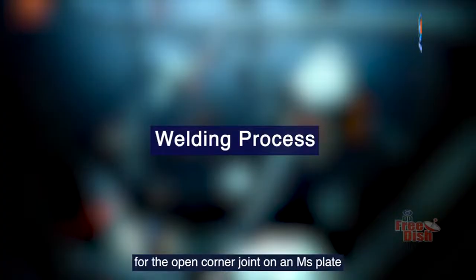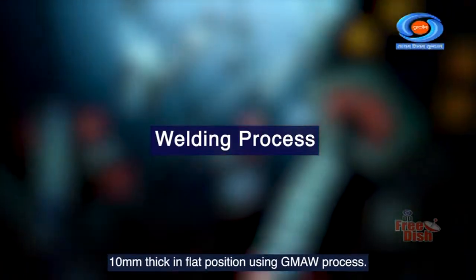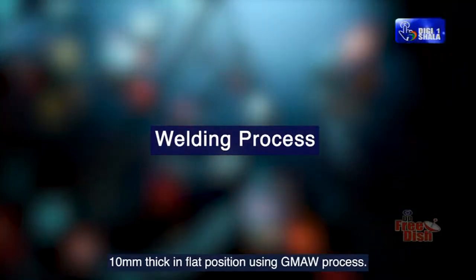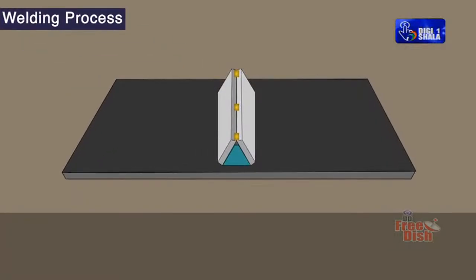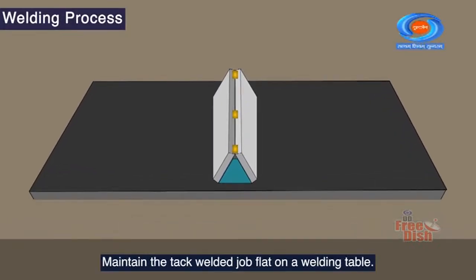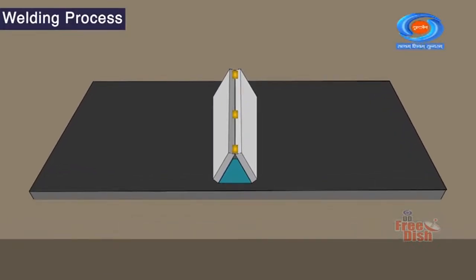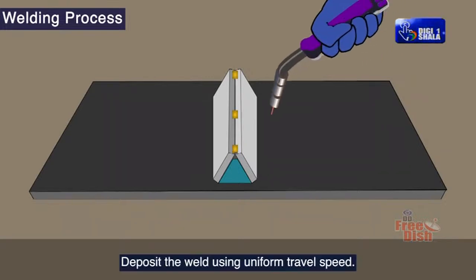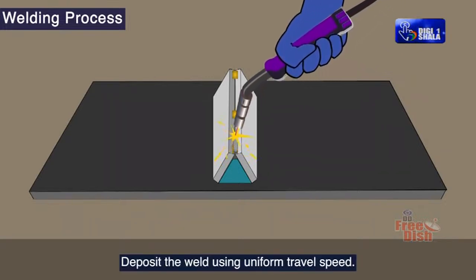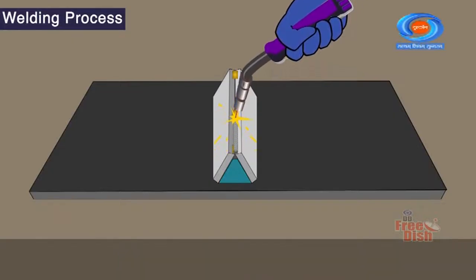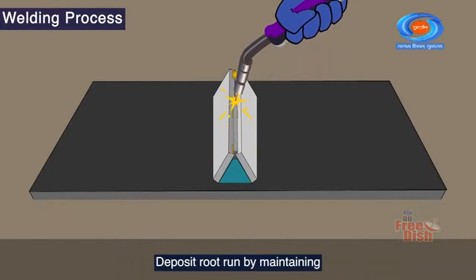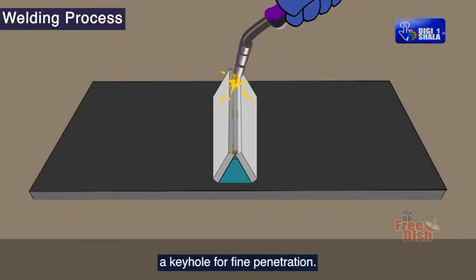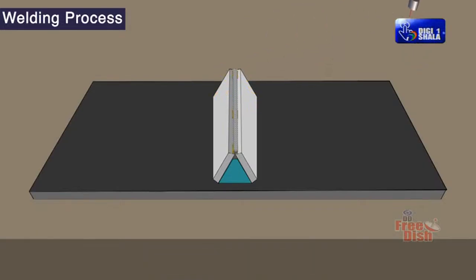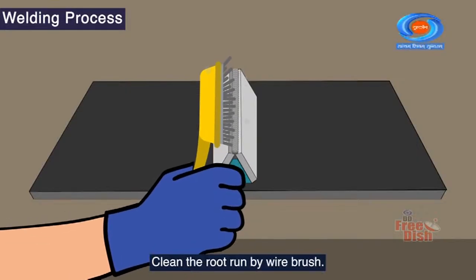Let us now go through the welding process for the open corner joint on an MS plate 10 mm thick in flat position using GMAW process. Maintain the tack welded job flat on a welding table. Deposit the weld using uniform travel speed. Deposit root run by maintaining a keyhole for fine penetration. Clean the root run by wire brush.